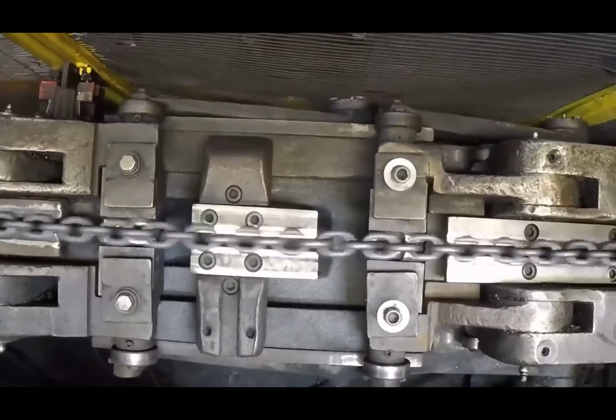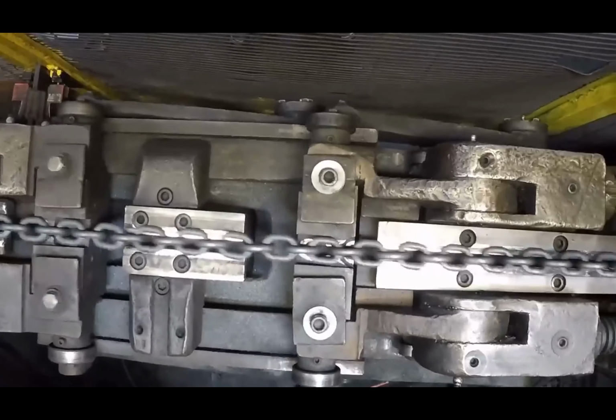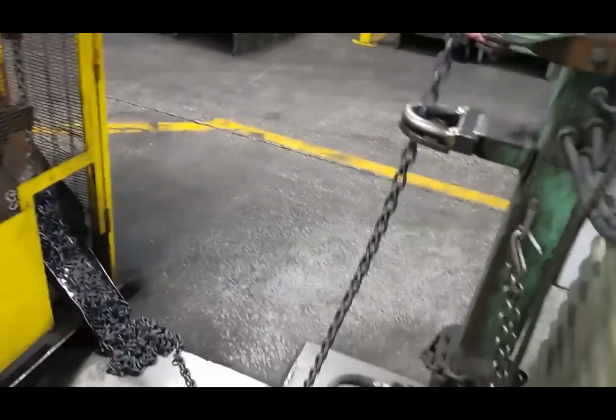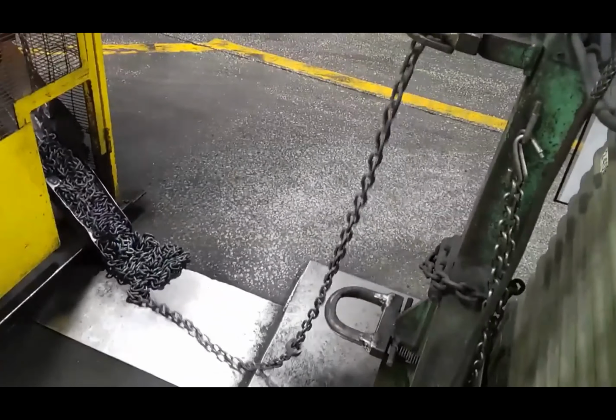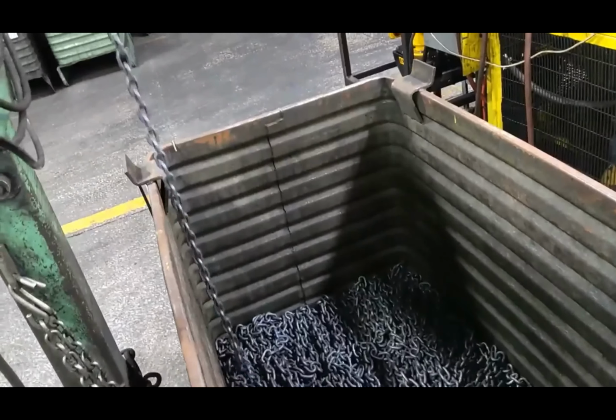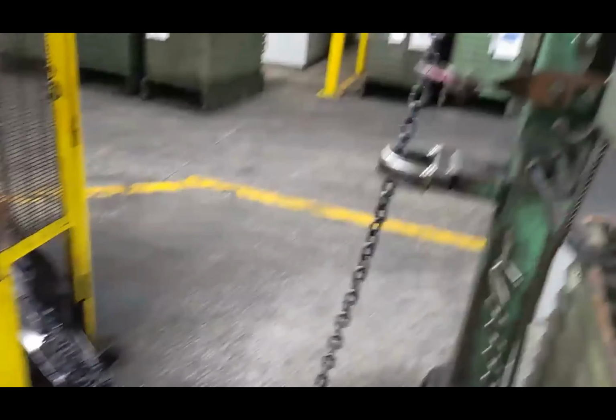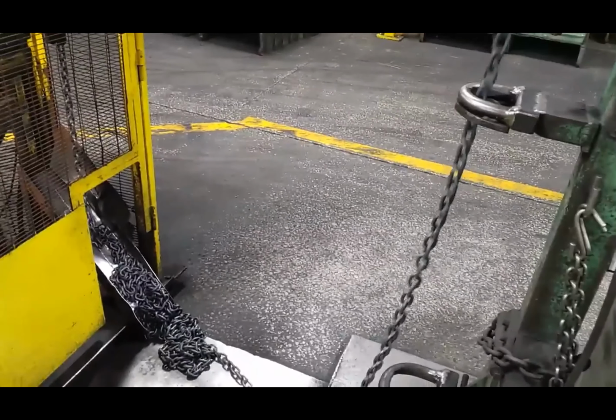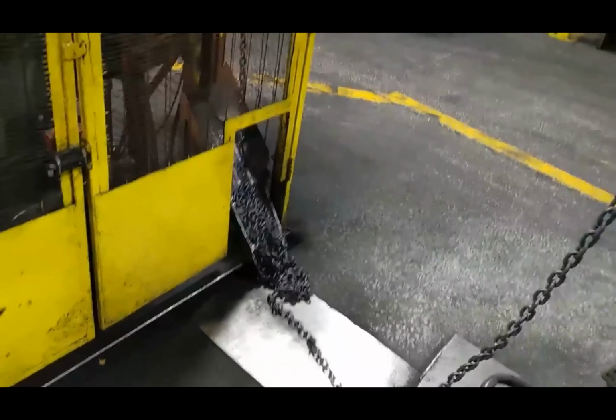But this type of destruct test is not only done when chain doesn't meet proof test value. We also do destructive testing where samples of the welded chain are cut from the production run several times per shift and are pulled to destruction to verify integrity of the weld and other physical properties. Speaking of destructive testing, let's join our quality inspector at our tensile tester where they're about to test some chain with one of our customers watching the process.